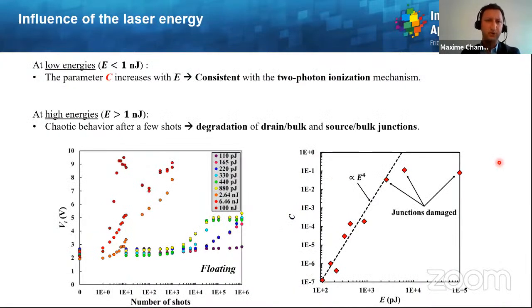In order to do so, we have evaluated the influence of the laser energy, as you can see here. Same kind of graph, the threshold voltage as a function of the number of shots. And one can see that for low energies, the parameter C increases with the input pulse energy, so the laser energy, which is consistent with the 2-photon ionization mechanisms, because the more the energy, the more the ionization, of course.